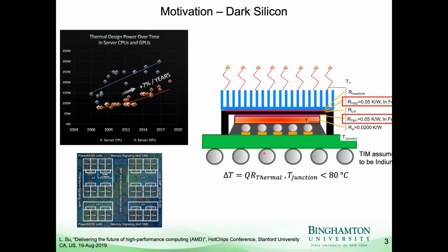You know, in the scheme of things, from the temperature the chip is at, 80 C, to ambient temperature, 20 C or 30 C, 5 degrees is not a huge issue. It's not dominating resistance. But as chips want to increase their heat flux to 500 and 1,000 watts per centimeter squared, this temperature drop across just the first thermal interface material can become significant, going up to, you know, as large as 50 degrees if you really were to increase to 1,000 watts per centimeter squared, as some hotspots are currently.